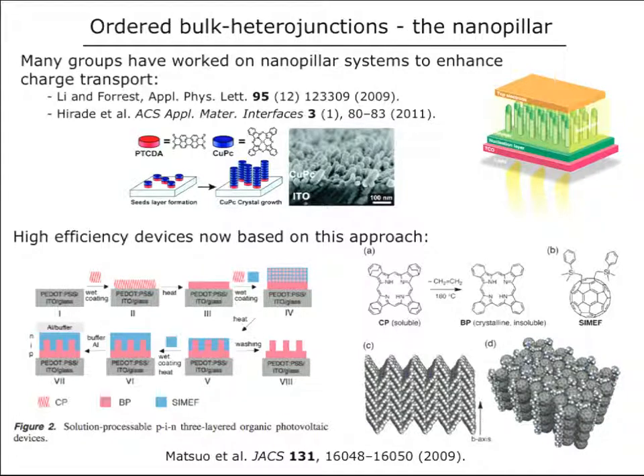And this is very important because the Mitsubishi result, the 10% result, is actually from such a structure. So what they have done is take a porphyrin material from a solution processable molecule, make a bulk heterojunction blend of that, but then thermally anneal it to induce growth of nanopillars, both of the fullerene and of the porphyrin. So now we have intercalated nanopillars of both components, and we get something that looks like the ideal, we think, cartoon of nice charge percolation pathways. So this was published a few years ago. As I said, more recent details are a little bit fuzzy, but it's a pretty good bet that the 10% device looks a lot like that in the active layer.